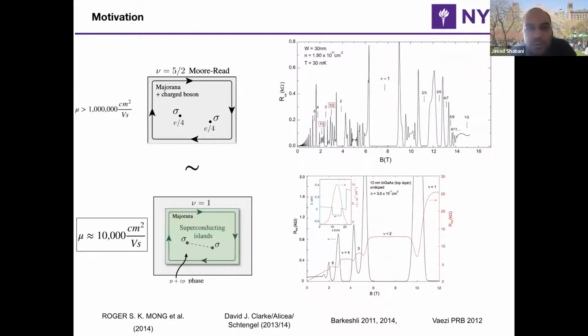I did my PhD in quantum Hall effect and in gallium arsenide. And one of the good goals there was to find these Moore-Read states or Pfaffian, anti-Pfaffian states around 5/2. And indeed, if you have a really good MBE, a really good low temperature system and push the limits, you can get samples that are in excess of 20 million mobility, and you can see 5/2 and 7/2. The idea was to control these states, to find out what is the nature of the ground state. But it's very delicate in the sense that when you try to gate these things, things fall apart. And that, to my understanding, still is a great challenge and is a great problem to attack.